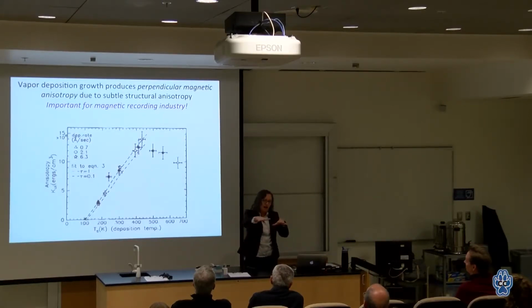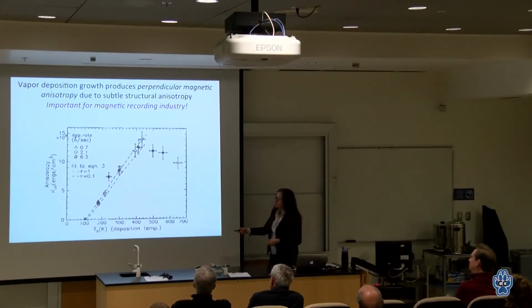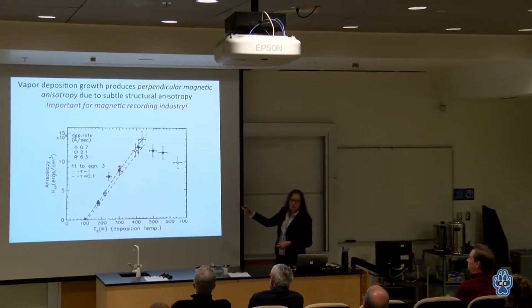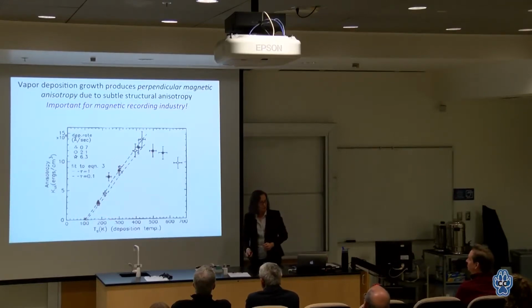So they have a lot of lateral mobility, but they have no vertical mobility. They get buried. So this anisotropy that I'm talking about is a remembrance of the way it grew, that out of plane is different than in plane. The interesting thing is that this anisotropy gets bigger as I go to higher growth temperatures.